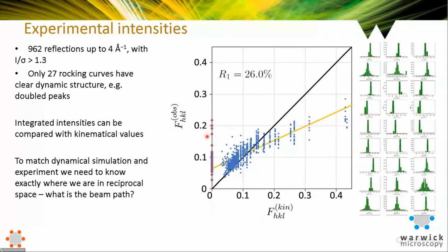Mainly, well, not only because, but one of the main things you can see here, in silicon, you have lots of systematically absent reflections which have zero structure factor, and they certainly don't have zero experimental intensity. So this is a big problem. And also you can see your strong beams are actually much weaker than you might expect, because they've all produced scattering into the other beams.